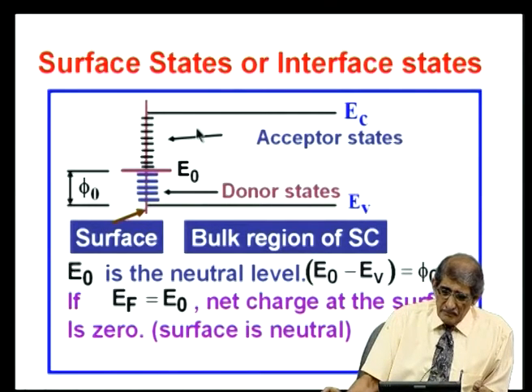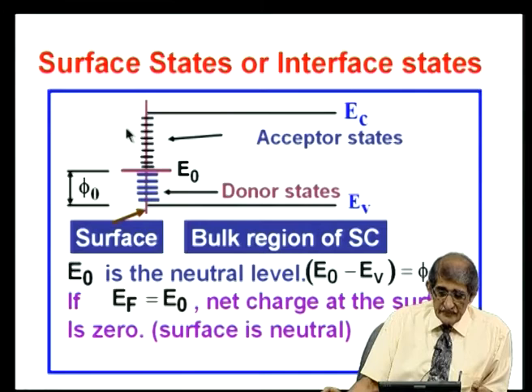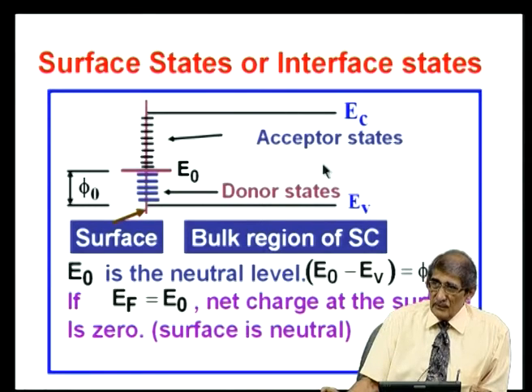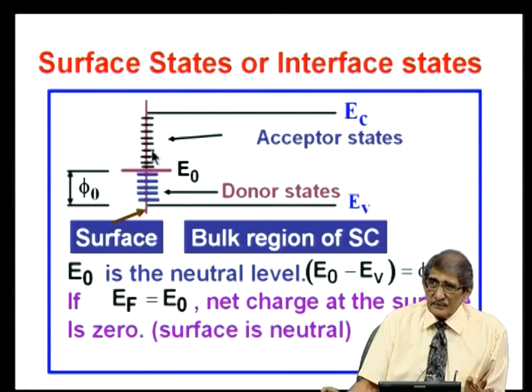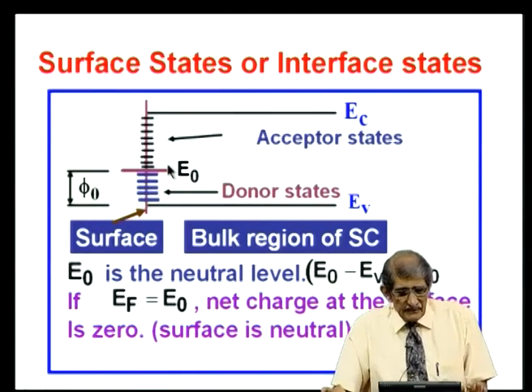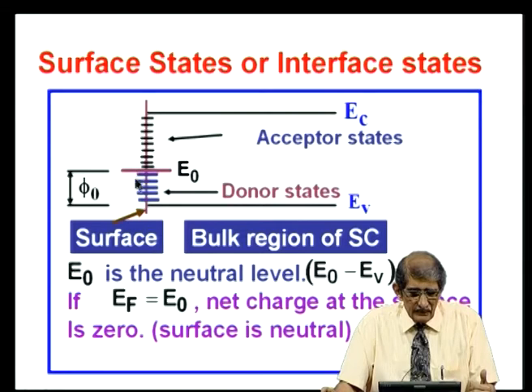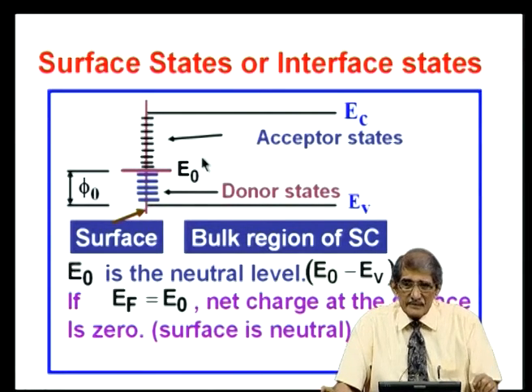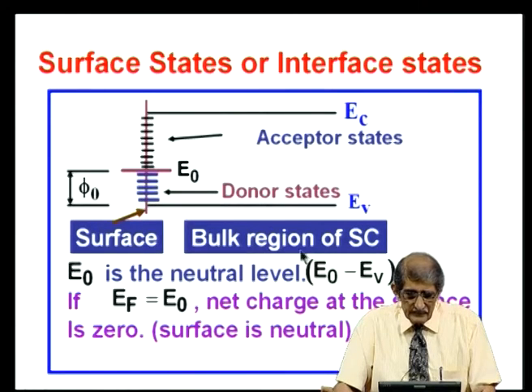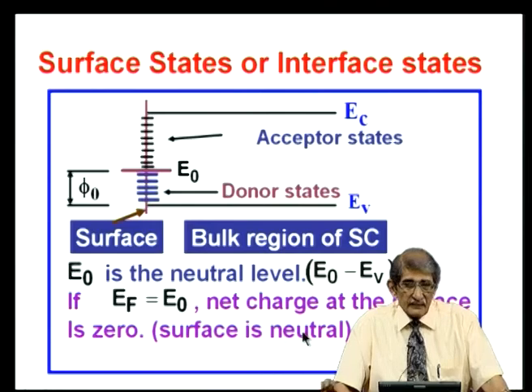So, to recap, if you take the surface of a semiconductor, there is a high density of interface states unless it is passivated, and they are all donors below a neutral level E naught, and above that they are acceptors. If the Fermi level coincides with E naught, all the donor levels are occupied, that is neutral. All the acceptor levels are not occupied, that is neutral. That is why we call it a neutral level. We represent the energy gap between E naught and the valence band as phi naught. E naught minus E v is phi naught. If E f is equal to E naught, the net charge on the surface is 0, the surface is neutral. This is what we have done.